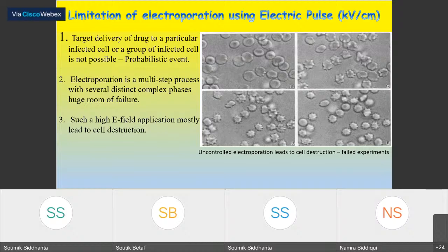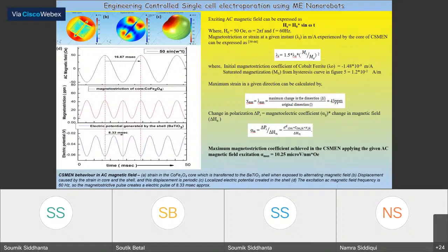Bulk devices were used, such big machines, to apply such a minute localized electric field. And the technique was also very uncontrolled, because it results in death of the cells, as you can see here, how these cells start deforming and creating permanent pores, and in the end result in cell death. So my target was, using this nano device that we fabricated, to open one single nanopore on one targeted cell and not affect any of the untargeted cells on its pathway.